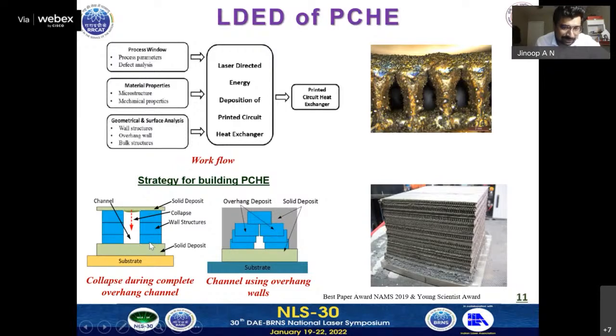We use a 3-axis LDED system for this particular work. And the major issue is that whenever we deposit the wall and try to deposit a solid deposit on top of it, it tries to collapse, mainly because of the gravitational effects. So because of that, we use overhang walls and we try to join to the top layer and we try to make a channel out of it. So with this, we did the trial experiments and we could find that the maximum shift that we can give is 15% of the track width for preventing the collapse of the walls.